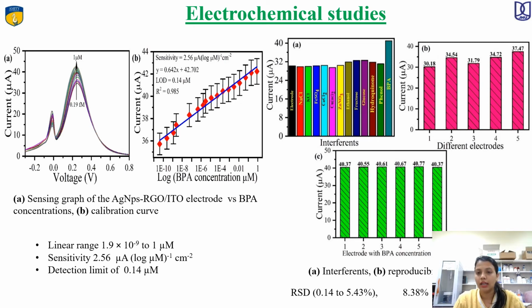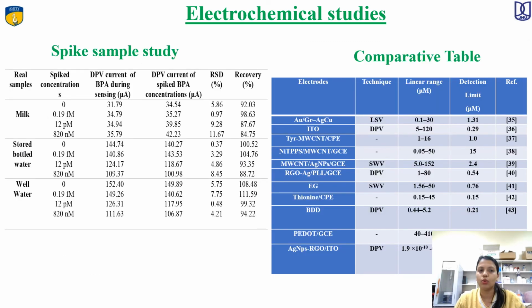Also, the interferent, repeatability and reproducibility studies were done, and they showed good relative standard deviation between 0 to 9%, which shows that they are quite satisfying results. Then next is the spiked sample study, as no BPA was detected in the real sample, so they were spiked with a specific concentration of BPA, and the relative standard deviation, that is the RSD, and recovery range were found in the acceptable ranges. And this is a comparative table showing the sensing parameters which are quite better than the previously reported ones.